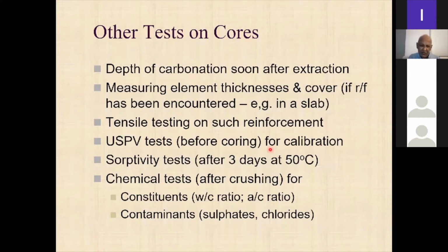Then you can try to do some ultrasonic pulse velocity tests before the coring for the calibration. If you core it, that means you have to use some water to make sure that the cutting bit does not get overheated, right? If you use water, then the moisture condition will change your ultrasonic pulse velocity, right? So it is always better to do the indirect test first. If you are doing the correlations, even rebound hammer, you can correlate with cores. But the rebound hammer test and the ultrasonic pulse velocity test that you are doing at the same place where you are getting the core, you have to do that before you take the core, right? When you take the core, of course, that point will no longer be there for one thing. And for another thing, even a close by point will be compromised by the moisture, right?